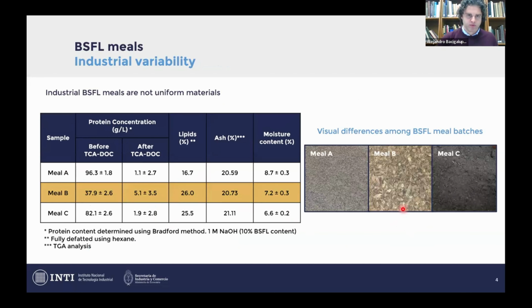But like most of you know, black soldier fly meals are not industrially uniform. Here we have some images of three meals that we use in our work that visually are already very different. We made some analysis to know the composition of these meals. We can see that protein content was also very different between them, and also other contents in these meals, like lipids. Of course, for our use, that is adhesives, we defatted all the meals with hexane because fat is anti-adherent, so it's a problem for us.